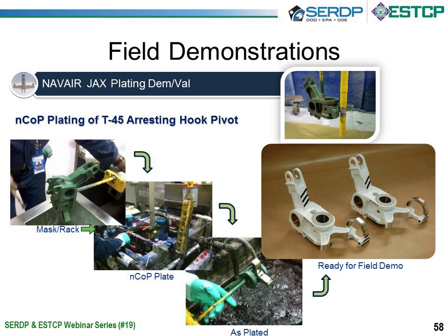So the first step of any plating process is to mask it. In this particular case, we are only going to be electroplating the cam face. This is a thermoplastic elastomer mask that we used. Due to the temperature at which this technology operates, conventional waxes that are used in electroplating are not able to be utilized. This particular maskant allowed us to selectively electroplate, although there were reported ease of use issues with this that we're addressing in the future work, and that will be discussed in a few minutes.